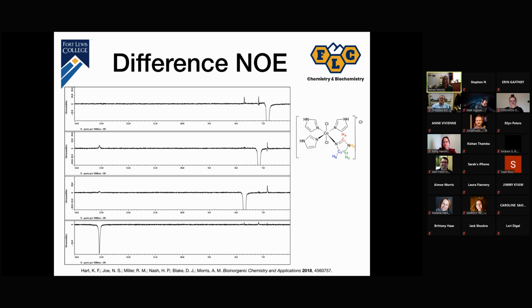And then when we irradiated that central aromatic proton that we were seeing, then you see a correlation to what ends up being proton B. And so we saw these different correlations, and when you irradiate what ends up being proton C, which is the furthest downfield of the aromatic protons, you see that NH is really interacting there. And so we were able to then go back by looking at irradiating these different peaks and finding the neighbors, which protons were correlating to which protons.